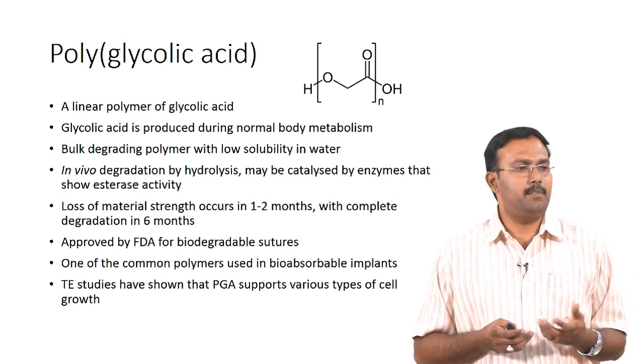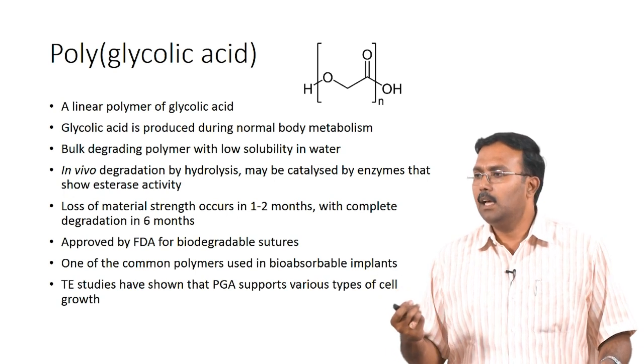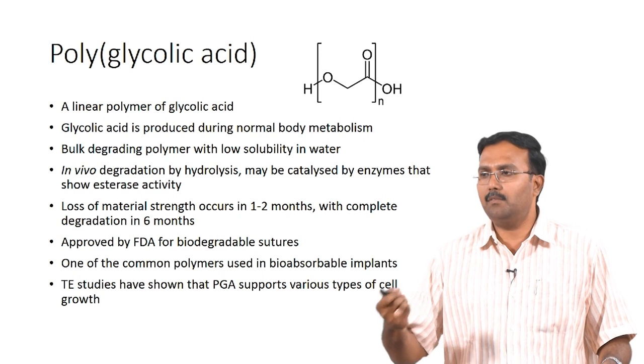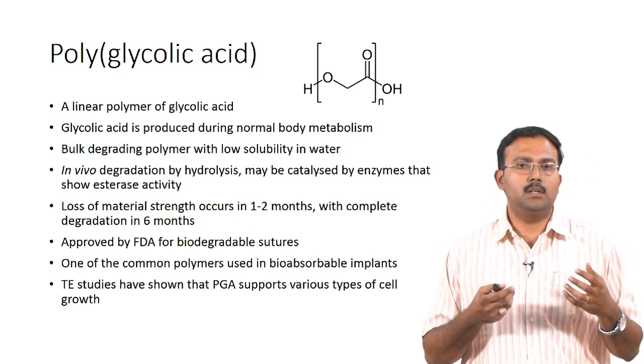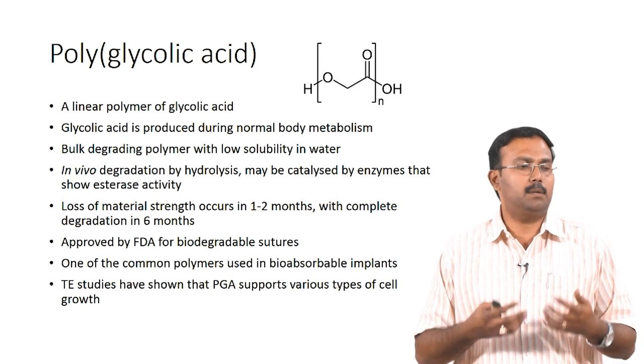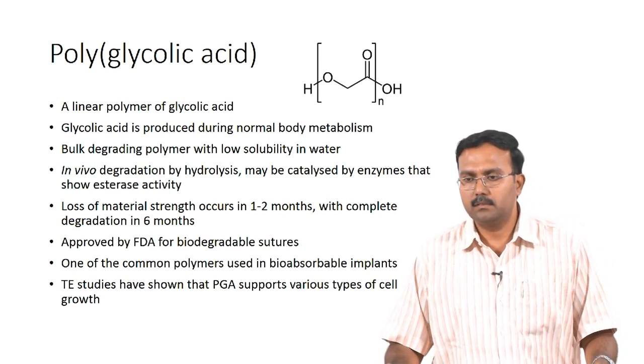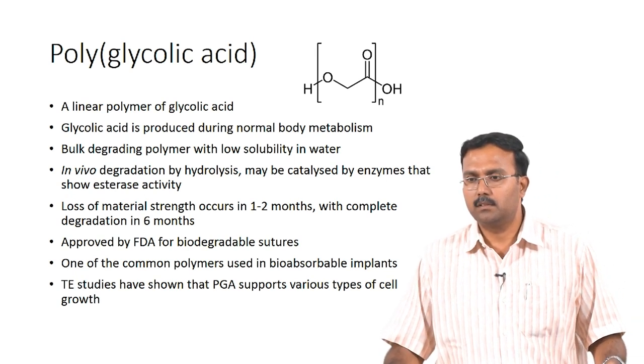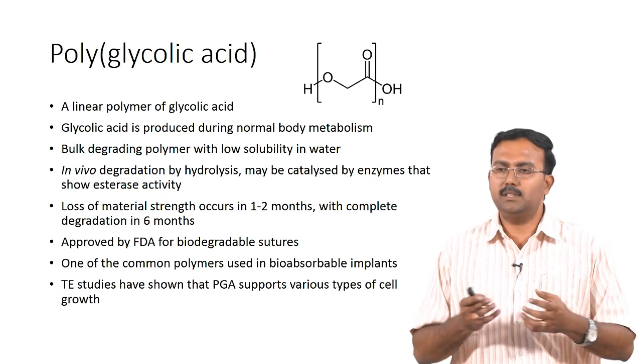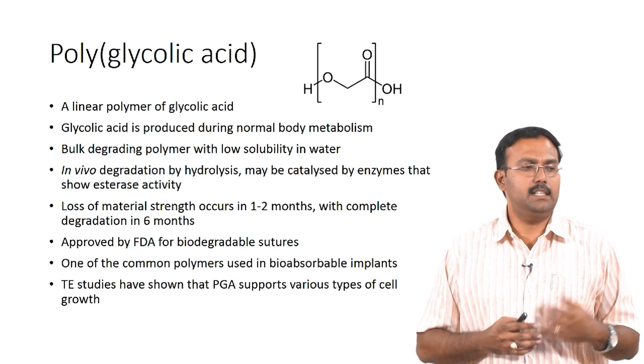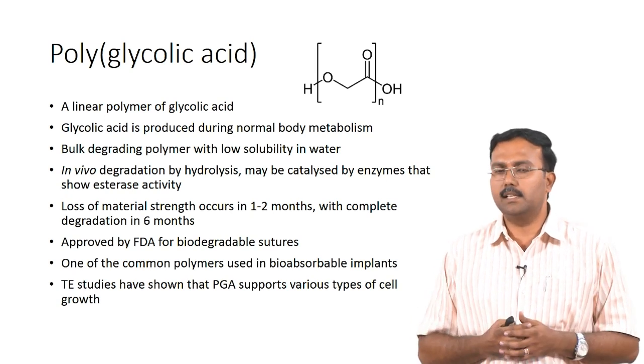In vivo degradation studies have shown that PGA usually loses its mechanical strength within the first 1 to 2 months, and complete degradation happens within 6 months. It has been approved by FDA for biodegradable sutures — people now use biodegradable sutures in surgeries so you do not have to go back for suture removal; they are absorbed by your body. This is one of the most commonly used bioabsorbable polymers, and tissue engineering studies have shown that different types of cells can actually adhere and grow on PGA.